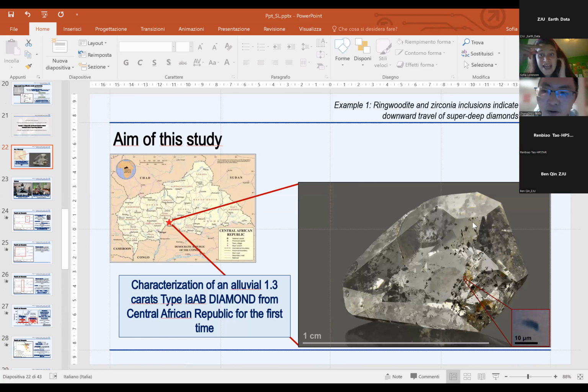here, this is a picture. So this is the diamond sample, and this diamond is extremely huge, because the longest dimension, sorry, of this diamond is 1 centimeter. And consider that this is not the original shape. The original shape was extremely irregular, but we cut the diamond because at the beginning we were not able to study the inclusion, so we needed a thinner layer of diamond for studying the inclusion with micro-Raman spectroscopy.